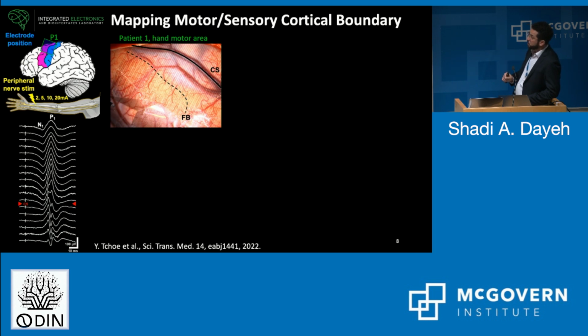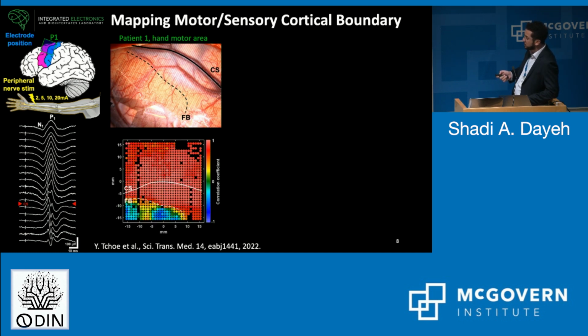Now, we've used this in the operating room of Dr. Aslan at OHSU, and the first procedure that's done is to define where we are at the surface of the brain once the skull is open. This is usually done in a procedure called central sulcus mapping or motor mapping, where an electrical pulse is applied to the peripheral nerve, and it evokes somatosensory evoked potentials. Once the phase of the somatosensory evoked potential changes from first negative to first positive, we know that there's a transition between motor to sensory regions. Now, this is typically anatomically marked with the central sulcus, where you have a blood vessel. But in the case of lesions in the brain, there is reorganization, and the only way to know where that boundary is is through functional mapping, the procedure that we just described.